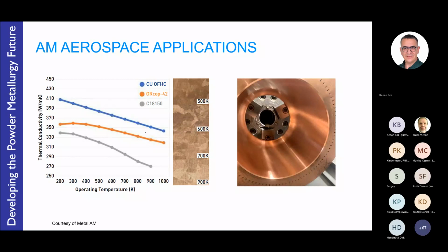And here you see a couple of examples of the different materials. And GRCop-42 is the copper chrome niobium alloy developed by NASA, the Marshall Space Flight Center. And the advantage of this material is it maintains its performance and strength, even though it's not that strong, at higher temperatures, while having a good thermal conductivity, again, operating up to high temperatures, up to its melting point. Melting point, of course, is about 1080 or 1082 to be precise. So therefore, it has to have internal cooling structures to maintain its material integrity.